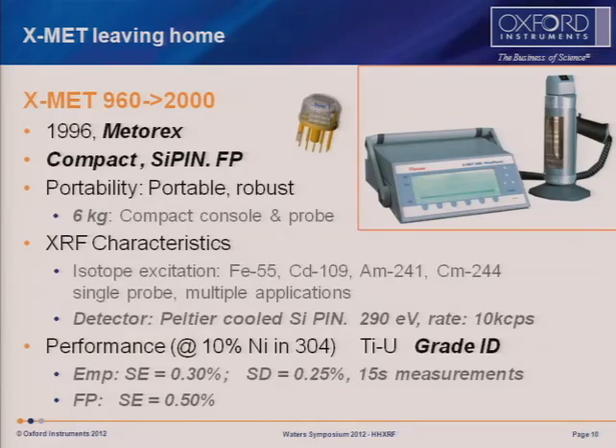The handheld probe worked successfully. But now we could do quite extensive grade ID with it, so it really was morphing into a stainless machine to go out and work on the plant. And it now was taking only 15 seconds. And in general, the standard error had now come down from 0.5 to 0.3, which is pretty impressive. Extremely good calibrations were set up for it, but in general needing a lot of standards and a lot of skilled operation, but much easier spectroscopy as a result of the new detector, which was developed in-house by the same team who had been developing proportional counters for the prior 20 years or so, and continued to develop this kind of detector.